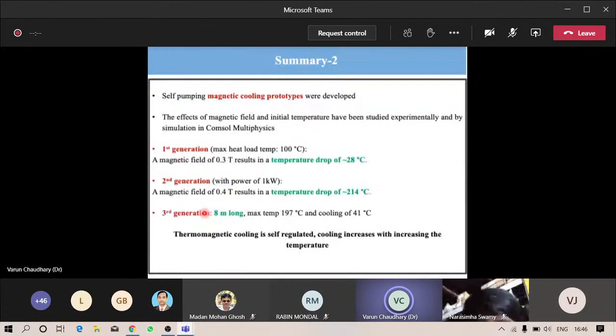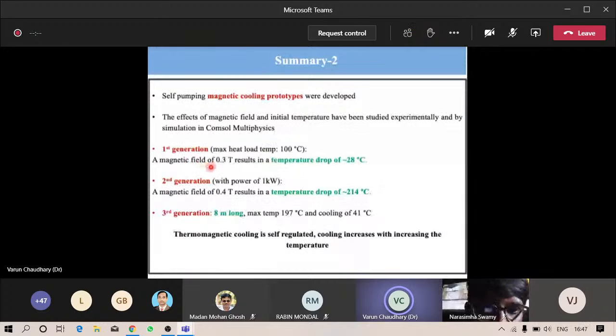So here the summary for the second half of the talk. The self-pumping magnetic cooling prototypes were developed. The effect of magnetic field and initial temperature have been studied experimentally and by simulation in COMSOL Multiphysics. I say that it's the first generation because I started work with that. In first generation, where we use the maximum heat load below 100 degrees centigrade and use the magnetic field of 0.3 Tesla, results a temperature drop of 28 degrees centigrade. In second generation, where we utilize this technique for kilowatt level, we applied a little higher magnetic field, 0.4 Tesla, and the temperature drop of 214 degrees centigrade was observed.